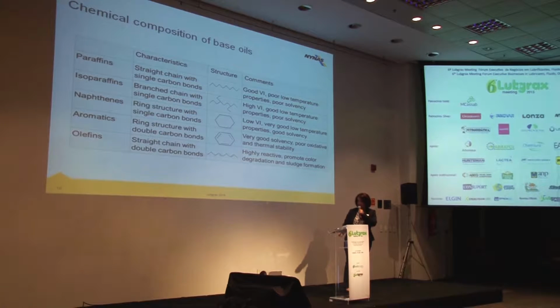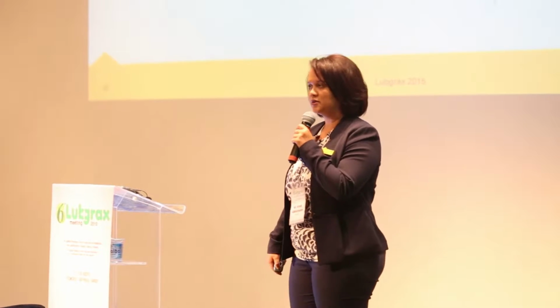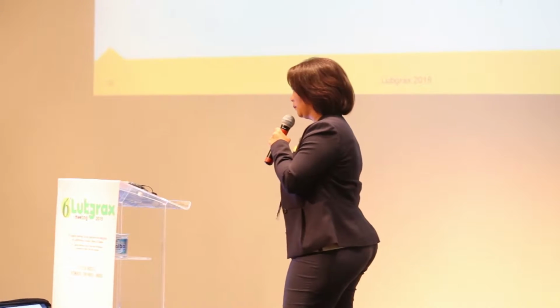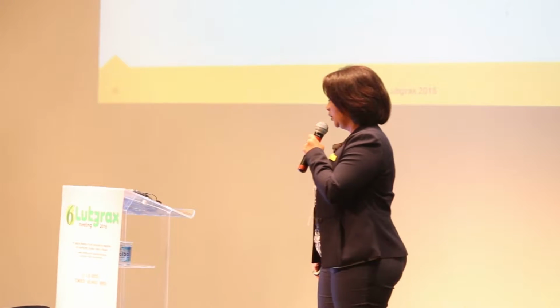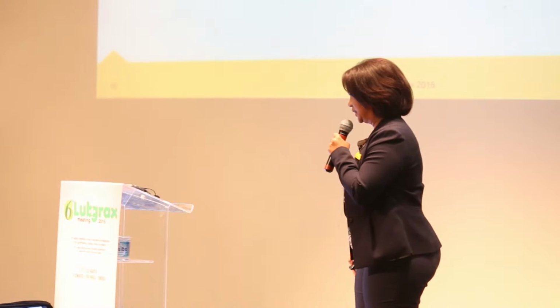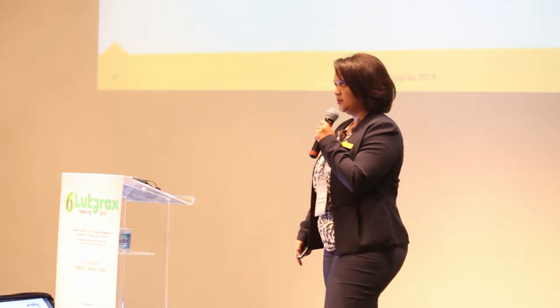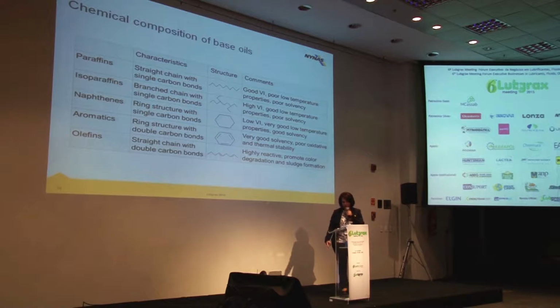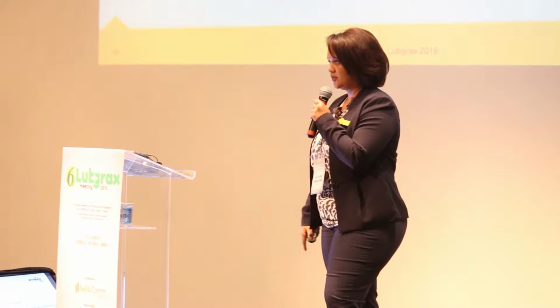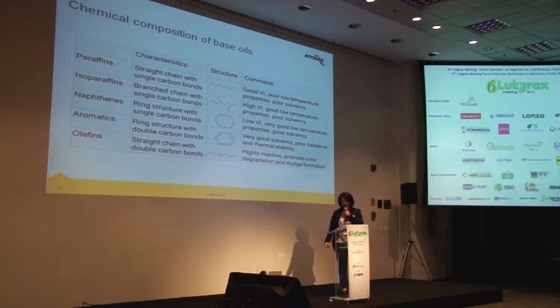So paraffins give rise to good VI, but usually, because they are normal alkanes, they are waxes and they tend to crystallize at low temperatures, so they give very poor low temperature properties. Also, poor solvency, and they usually have a very high pour point. Isoparaffins have much higher VIs. Naphthenics, which are ring-like structures, are low VI. They have very good cooling properties, good low temperature properties, and good solvency.